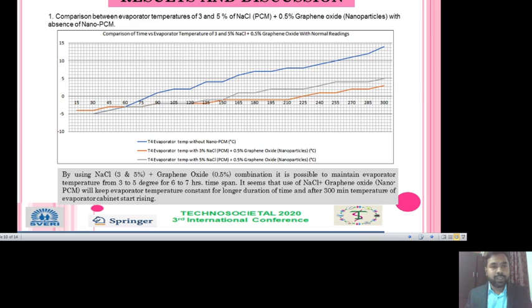The first graph compares the evaporator temperature, or cooling chamber temperature, for 3% and 5% NaCl along with 0.5% graphene oxide nanoparticle, with and without the nano phase change material. The blue line indicates that the temperature keeps increasing inside the deep freezer when we do not use the Nano PCM container. By using the NaCl combinations, 3% and 5% along with 0.5% graphene oxide, it is possible to maintain the evaporator temperature at 3 to 5 degrees and extend the cooling time up to 6 to 7 hours. So NaCl plus graphene oxide nanoparticle keeps the evaporator temperature constant for a longer duration even though a power outage exists.